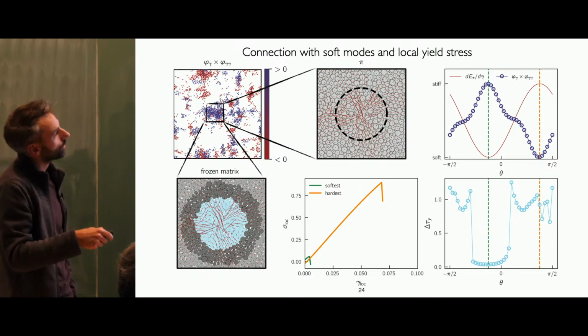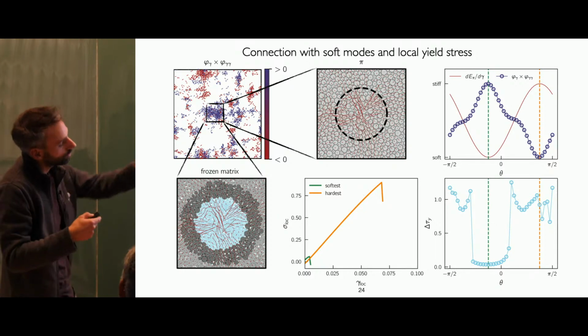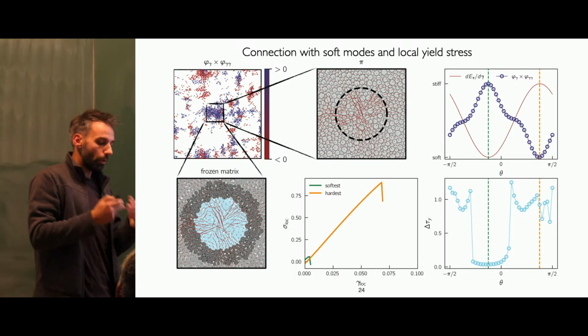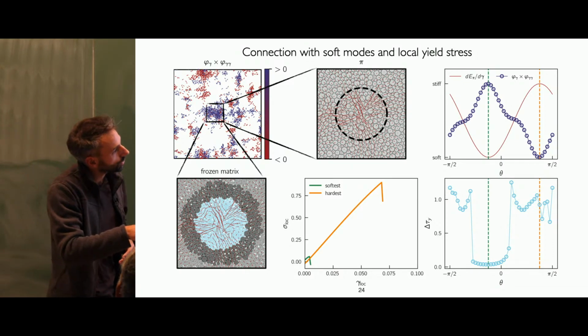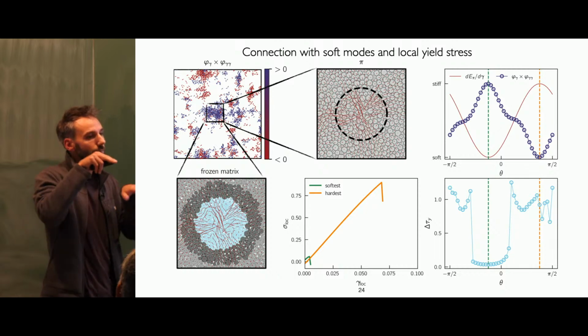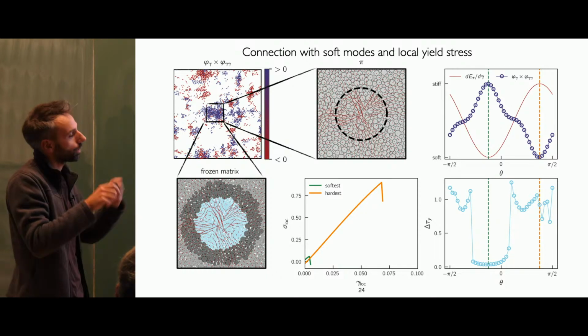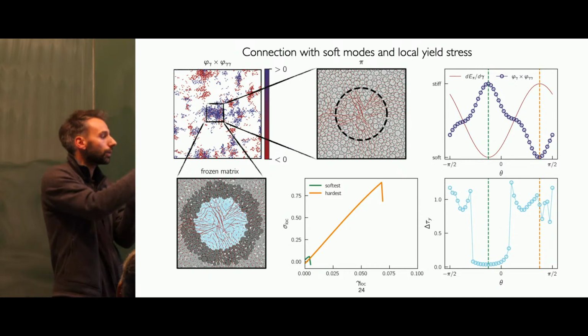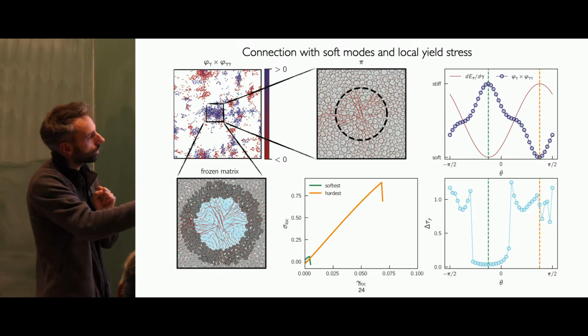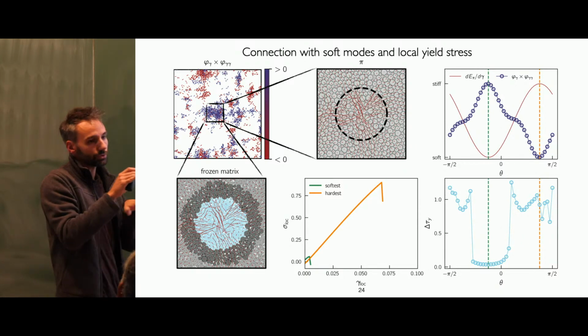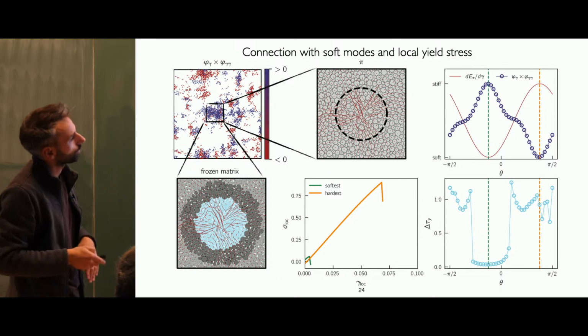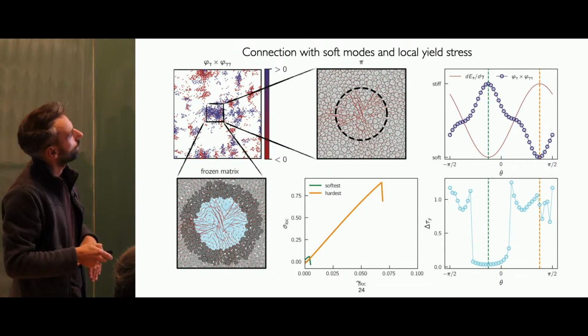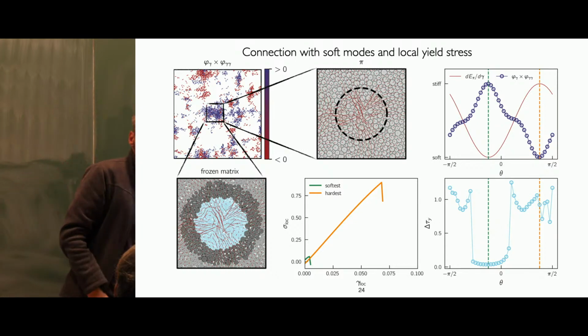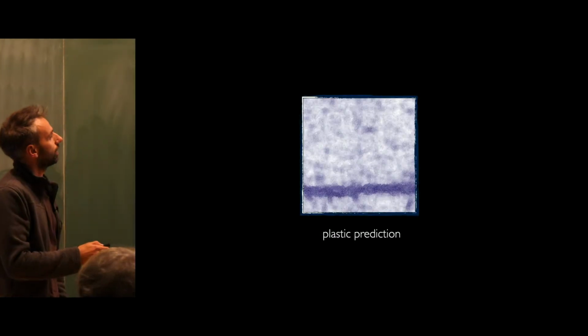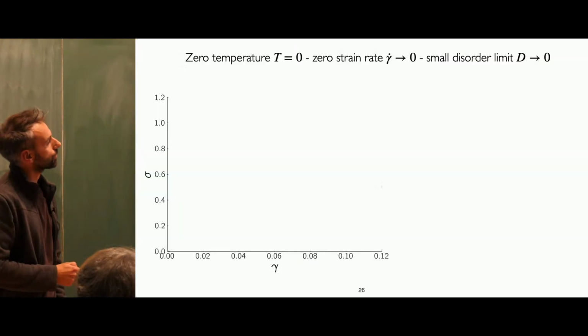What is absent in this picture is that the local yield stress not only gives you maybe the most favored direction, but it also gives you an indication of other yield planes. So you imagine that if you take a packing like this, there is not only one direction where you will be able to flow. There are actually many angles where the system will be able to undergo a transformation. All right. How long do I have? It's almost time. Okay.